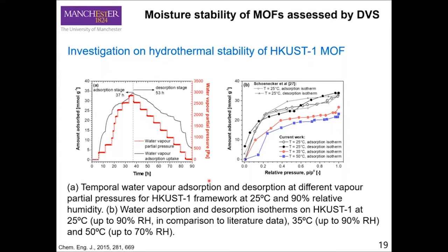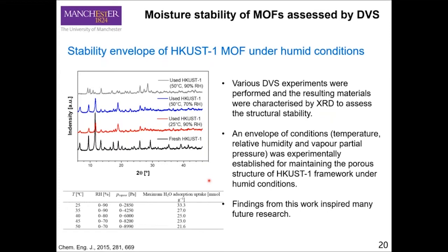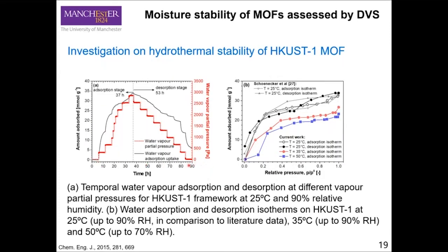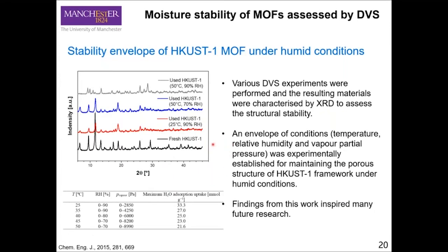And this work is quite interesting because, based on that, we have done lots of experiments using DVS. They are, as I said, very time consuming. But the good thing is we know basically the material is hydrothermally not stable. So therefore, the key information from this work is we try to use the DVS to assess the window of this material to be stable under different conditions.